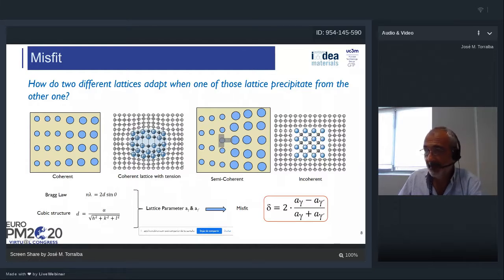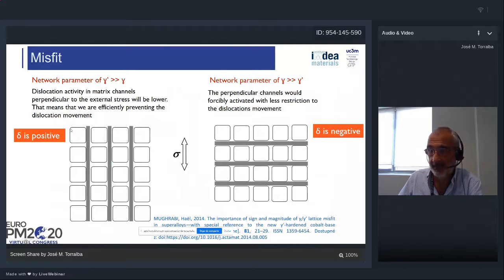So another interesting thing is that if the lattice misfit is positive, that means that the lattice parameter of the gamma prime is much higher than the gamma. We used to have dislocation activity in the channels of the gamma phase perpendicular to the applied force. So that means that we have a more efficient way to prevent the dislocation movement, and in that case, higher mechanical properties, especially at high temperature.